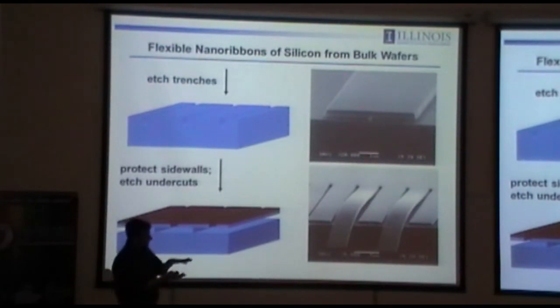The first one of which is that the silicon wafer has this lack of bendability, partly because of the intrinsic mechanical properties of the material, but also because the wafer is a millimeter thick. If you think about how the bending rigidity scales with thickness, it goes with the cube of the thickness. So if you decrease the thickness by a little bit, you impact by a huge amount the bendability, the ability of the silicon to flex. And in fact, if you take a silicon wafer, and there's a two-step etching process that you can use with a silicon 111 wafer to allow you to slice very, very thin, sort of 100 nanometer thick ribbons of device quality silicon off the surface of the wafer.